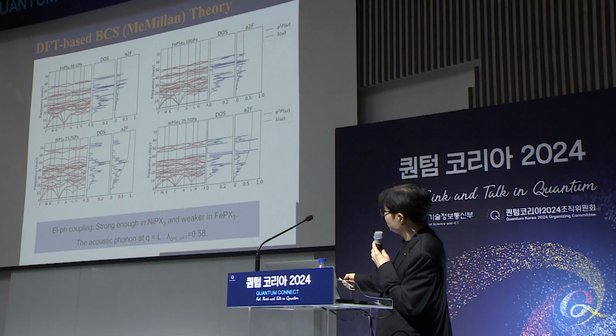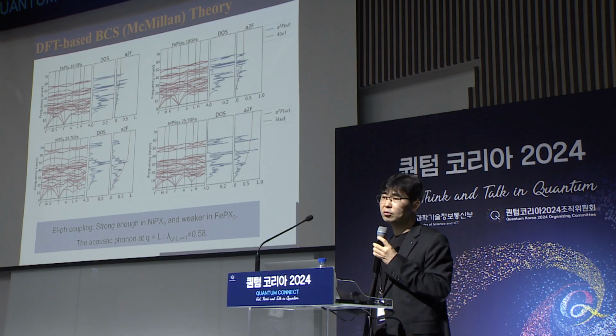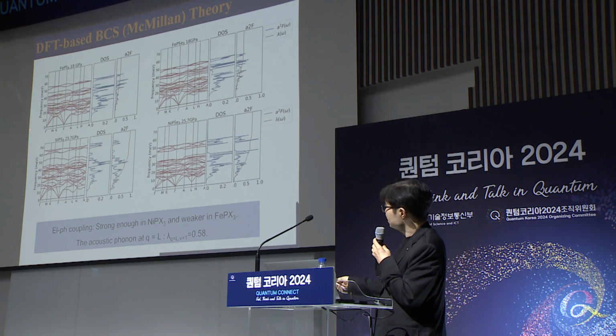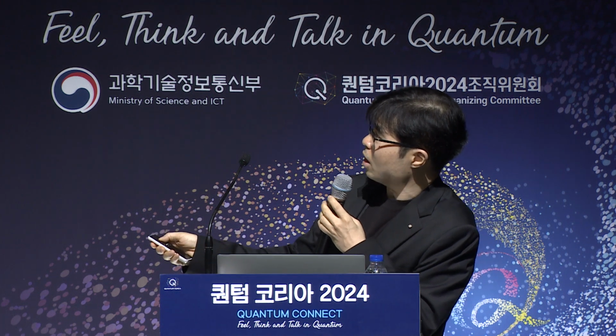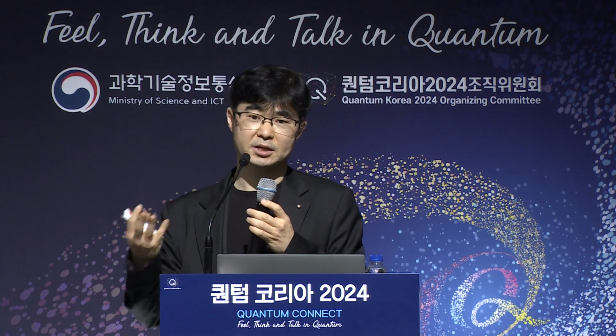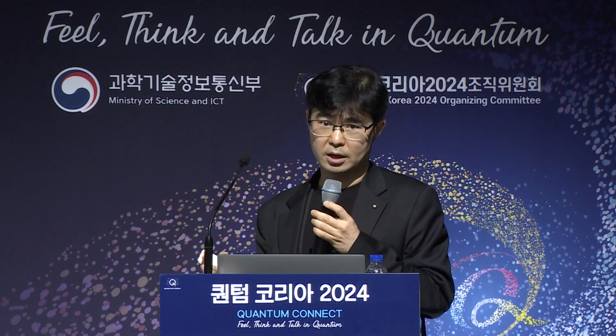This is a kind of standard computation scheme. The first thing we want to do is to examine the so-called phonon band dispersion and phonon density of states. A phonon is a lattice vibration, or coherent atomic movement, in a given material. The red colored line we call phonon bands, and the blue colored line we call phonon density of states. And this alpha square F, we call the Eliashberg function, which contains the key information regarding BCS type superconductivity. By looking at this function, we can very nicely guess whether the material is superconducting or not, okay?